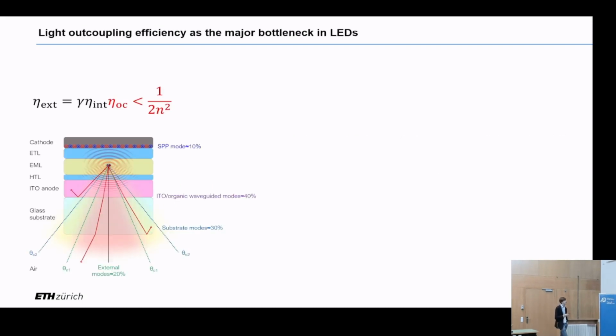Which is what motivated us to look into the next big efficiency bottleneck of LEDs, which is light outcoupling. We already heard a bit about it, and it's a bit of a tricky one because it's an intrinsic limit of planar light emitting devices. It has to do with the fact that light, so photons, are generated within a material which by definition is denser than air, so total internal reflection is unavoidable. And of all the photons that you generate, only a subset, those whose angle lie within this extraction cone, can effectively be counted as output photons, and that limits the efficiency.